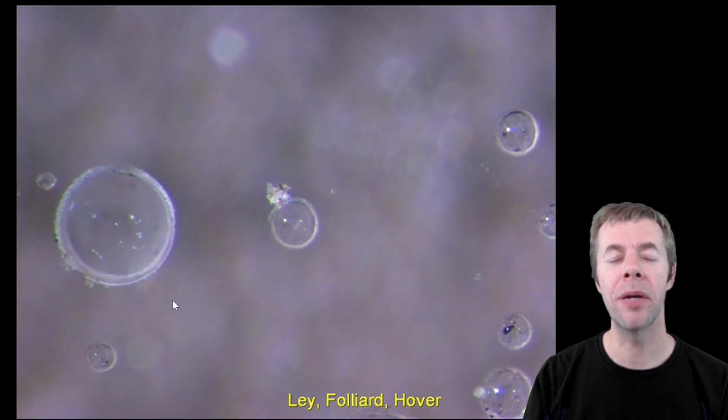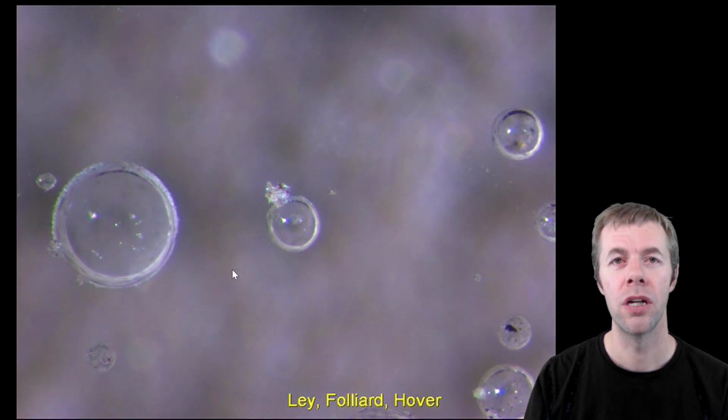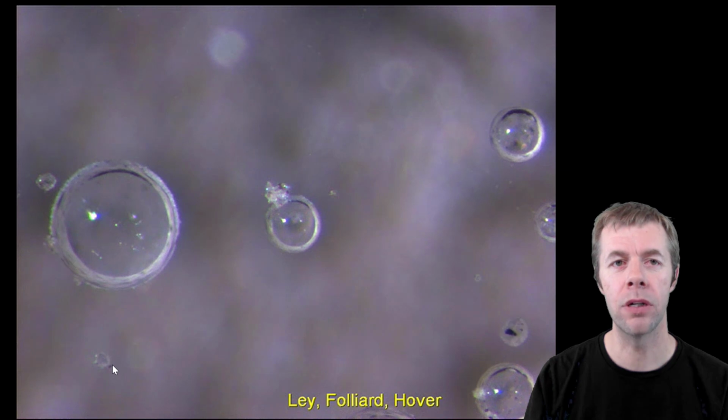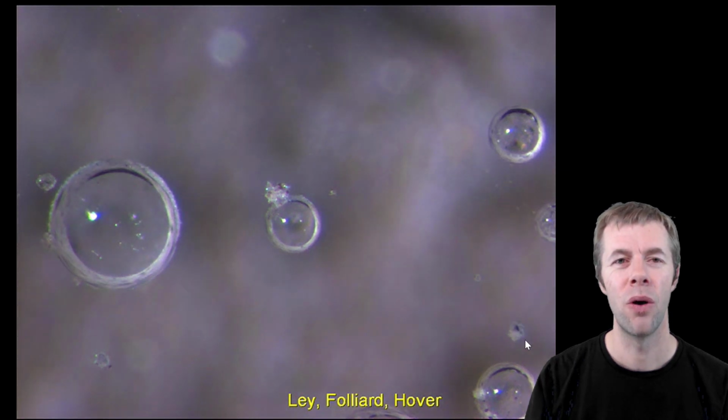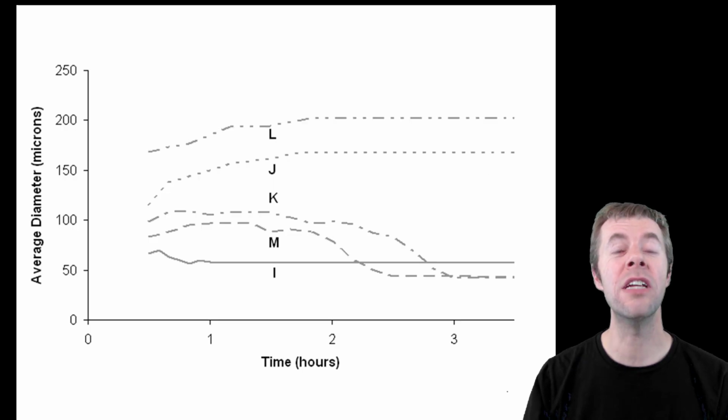Now we can see over time, again, every second is 5 minutes, and the larger bubbles are getting larger, right? You see them? And these smaller bubbles, look at that one, get smaller. Look at that one over there. Look at that. What is going on? There's actually air interchange happening between the bubbles, okay? This is widely known in physics, okay?